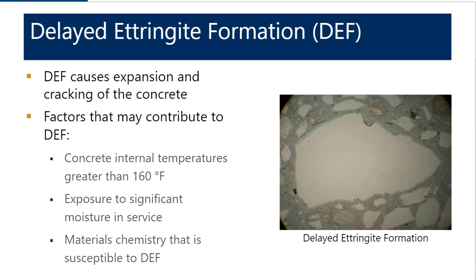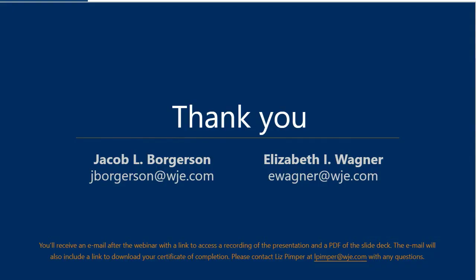Okay, our next question. What is the average length of time for monitoring, the temperature control period, and how is this determined? So the temperature control period is basically defined by how long you need to keep your insulation in place until the risk of thermal cracking is minimized. And so we talked about thermal cracking being driven by the difference in temperature between the interior of the concrete and the surface. And so really it's how long until the temperature at the interior of your placement is within the allowable temperature difference from the ambient temperature.